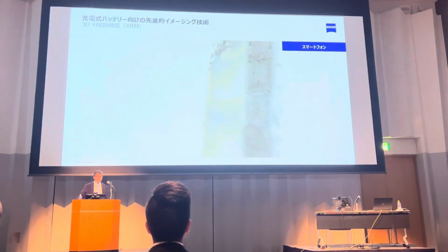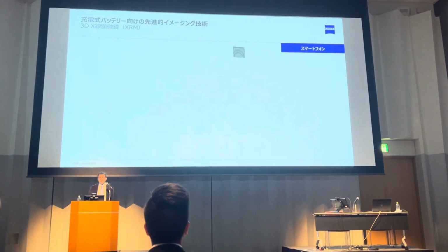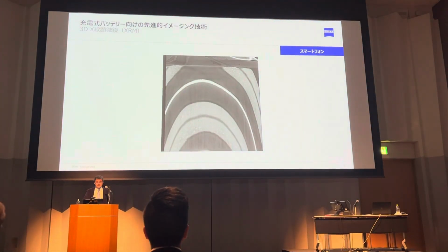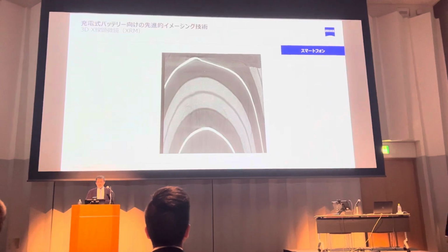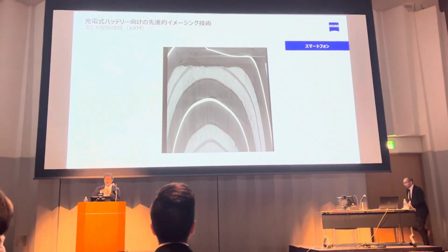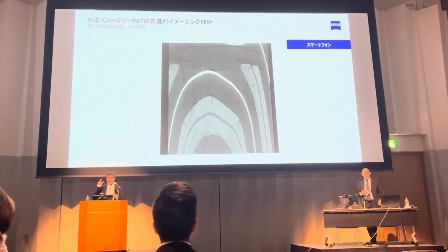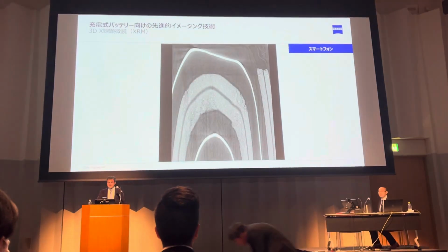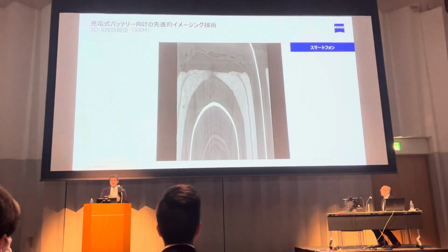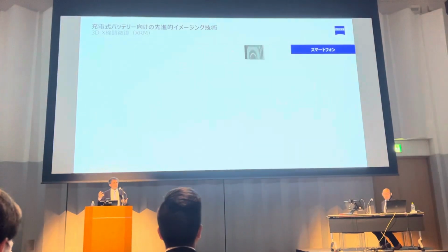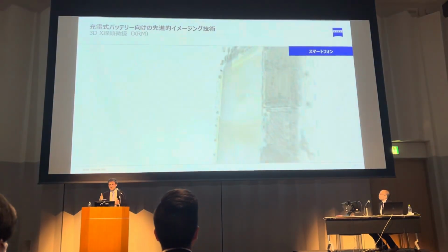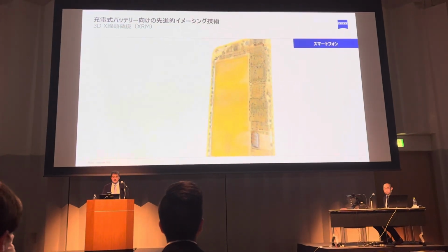And this example shows now how we can scan a battery that goes into a smartphone. And you can see all type of features. Not only you can image the full smartphone, but now target the small features in the battery to see any traces of degradation after several cycles of charging and discharging, to the point that you see some delamination over there.